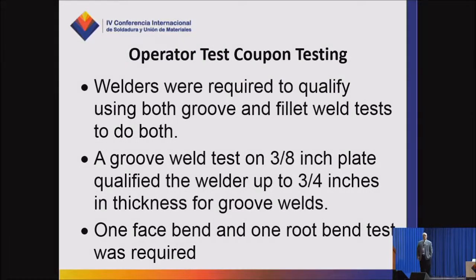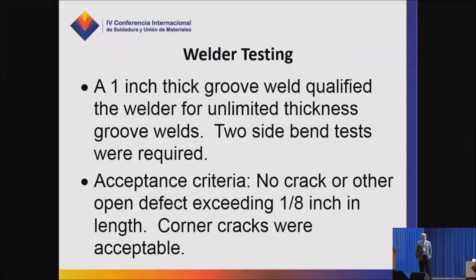What about the testing of welders? What kind of test did the welder have to take? Well, if a welder was going to use groove welds and fillet welds, he had to do a groove weld test. He also had to do a fillet weld test. Groove weld test on 3/8 inch thick material qualified the welder to 3/4 of an inch in thickness. Same as procedure. One face bend was required. One root bend was required. A 1 inch thick test gave the welder unlimited thickness.